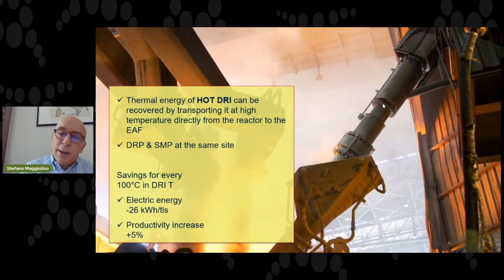If we combine high carbon DRI with hot transport, we have additional benefits. We've been the first plant, the first technology, to use transport of hot DRI. For each 100 degrees of temperature in the DRI, we save at least 26 kilowatt hours per ton of liquid steel, increasing the productivity by 5%.